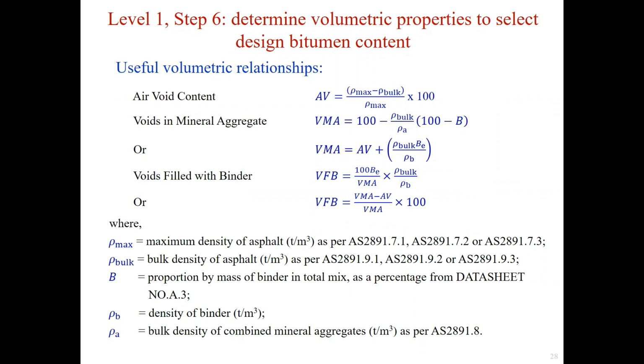Rho bulk is the bulk density of asphalt in tons per cubic meter. Capital B is the proportion by mass of binder in the total mix. Rho B is the density of binder in tons per cubic meter. Finally, rho A is the bulk density of the combined mineral aggregates in tons per cubic meter.